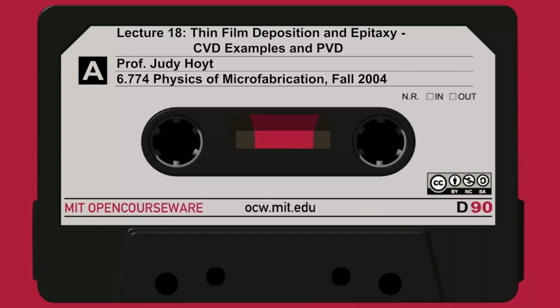And why is that? Well, the back-end has to use it because typically you need very low temperatures. But if you go to slide 12, the characteristics of plasma-enhanced CVD deposited films like oxide or silicon nitride can be quite different from those that are deposited at higher temperatures by LPCVD. For example, very different amounts of stress in PECVD and LPCVD films. Hydrogen content in particular, make a note, PECVD films tend to be loaded with hydrogen. I mean, a lot, could be like 10% hydrogen. They're just stuffed with hydrogen.